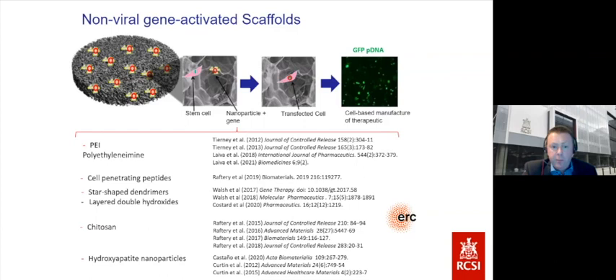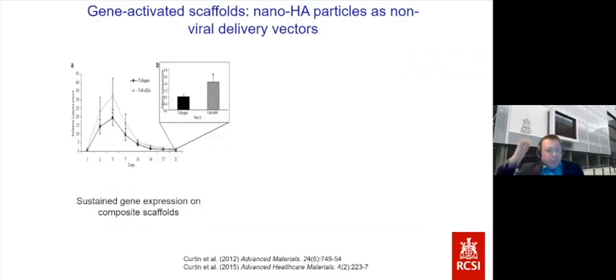Next slide, please. So to give you an example, and again, for the people who are more interested on the material side, what you see on the slide on the left is the expression profile of the gene expression from the scaffold system. So you get this increase in gene expression up to maybe day 7 to 10 to 14, depending on how we want to control that. And then it begins to drop off over time. And we can manipulate how long a gene is expressed and how long the cells take up that gene by changing the cargo or the nanoparticle composition, and by also controlling how we manipulate the scaffold.